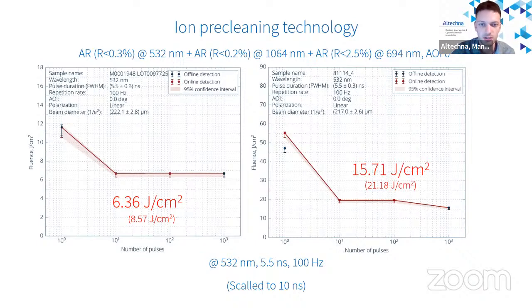And once we did pre-cleaning, we managed to achieve more than 21 joules per centimeter square, also scaled to 10 nanoseconds. These measurements in this case were done at 532 nanometers. So these are just two very short examples of what we're able to achieve. Thank you for listening, and let's keep in touch.